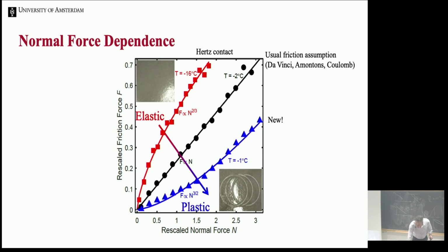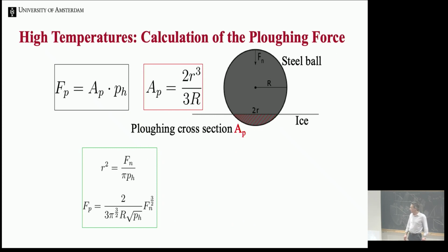And we go from elastic to plastic. So let's first do the plastic part, because it's actually the easiest. What we have is a sphere that is moving through part of the material. The penetration force, the normal force, is given by the penetration hardness of the ice, the limit at which the ice starts to deform plastically, times this area.